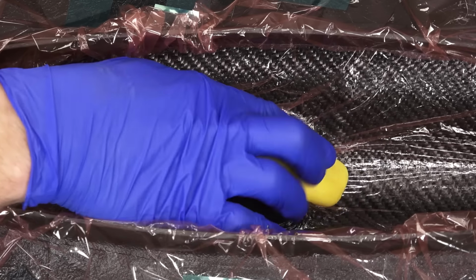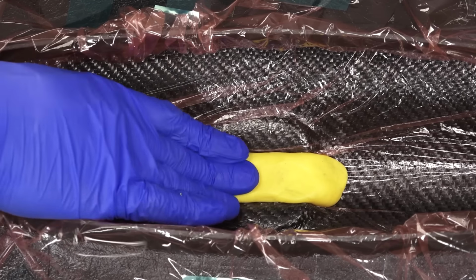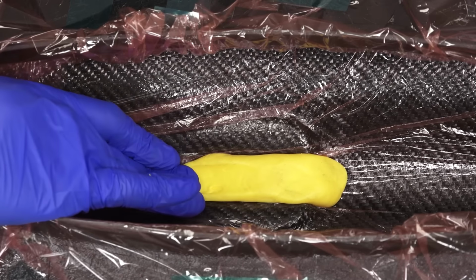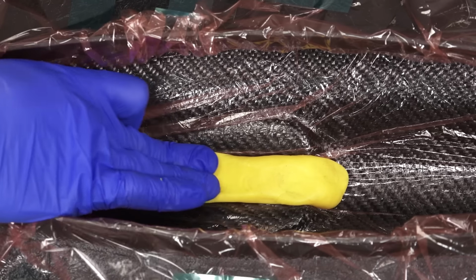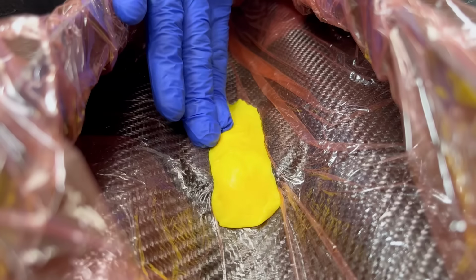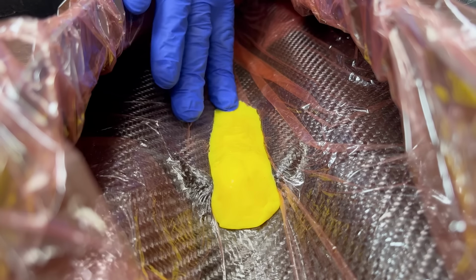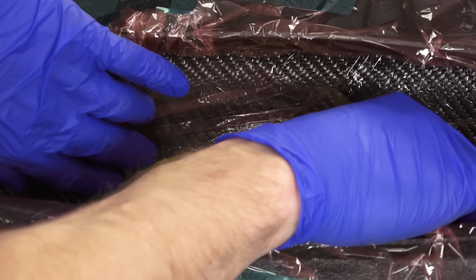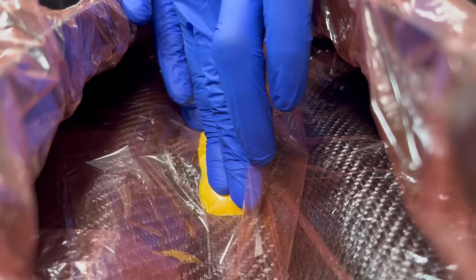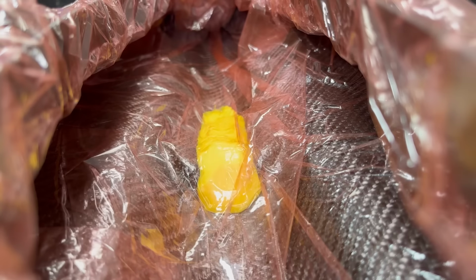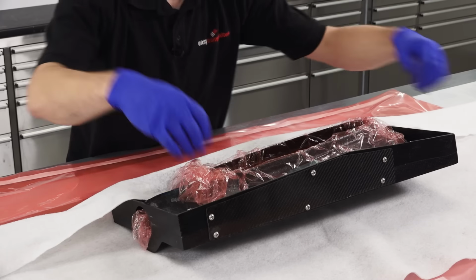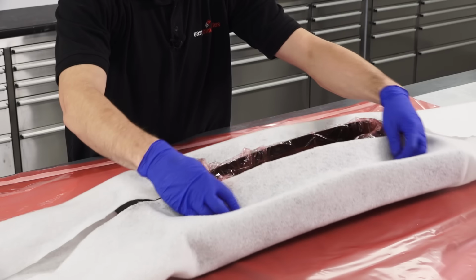The material is worked into the surface in just the same way as we did for the wings. Again, blending it into the part surface to ensure that we don't get a sharp transition that could lead to print through. This is then covered in a layer of release film to prevent it from sticking to the vacuum bag, and now the entire part can be wrapped in breather, vacuum bagged, ready for cure.